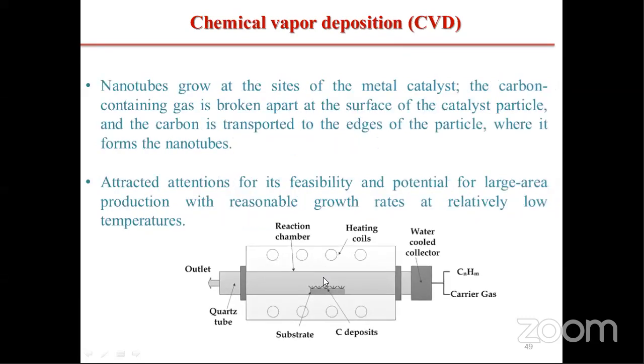Once they are fed into the reactor, they start to heat at 700 degrees Celsius. Once they start to heat, nanotubes start to grow at the site of the metal catalyst. The carbon-containing gas is broken apart at the surface of the catalyst particle, as a result of which the carbon is transported to the edges of the particle, where it forms the nanotubes. That is, nanotubes will start to sit on the surface. Chemical vapor deposition is a very simple method, and it has attracted attention for its feasibility and potential for large area production with reasonable growth rates and at relatively low temperatures.